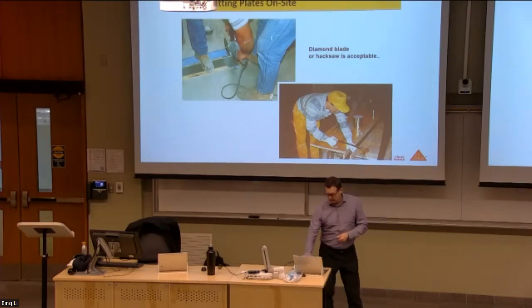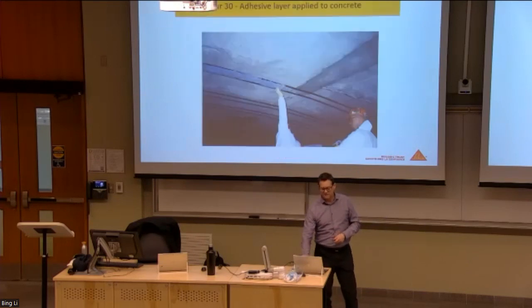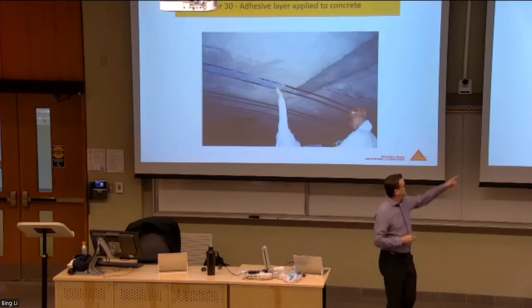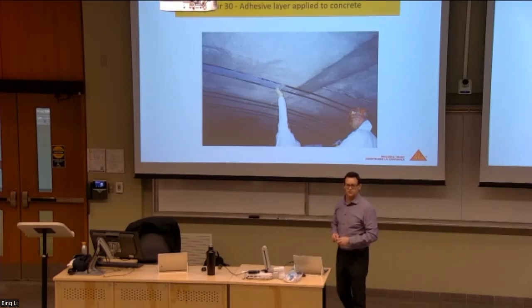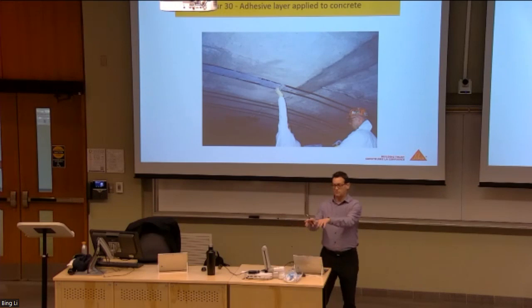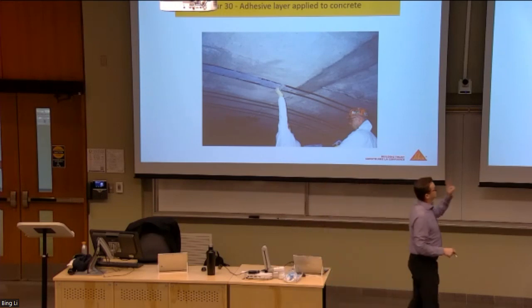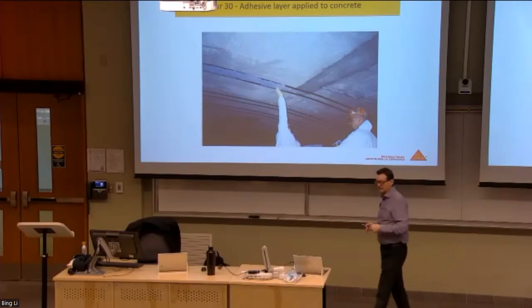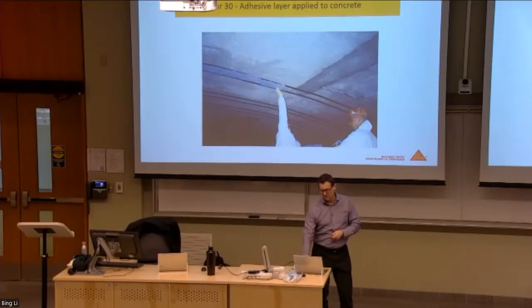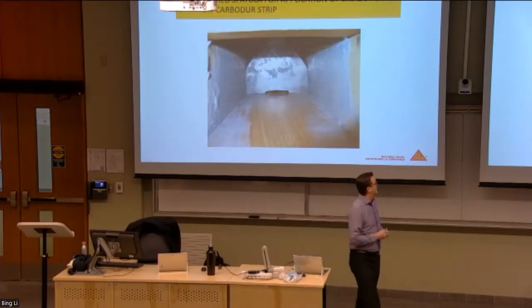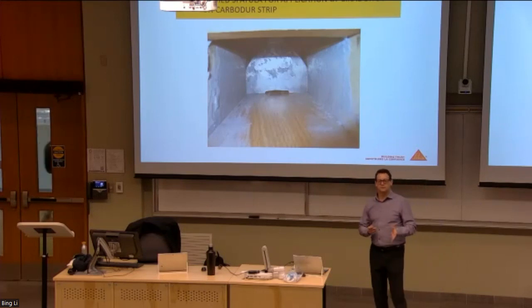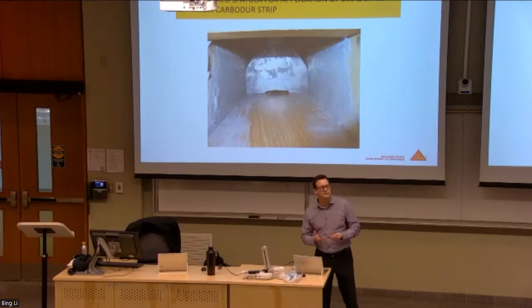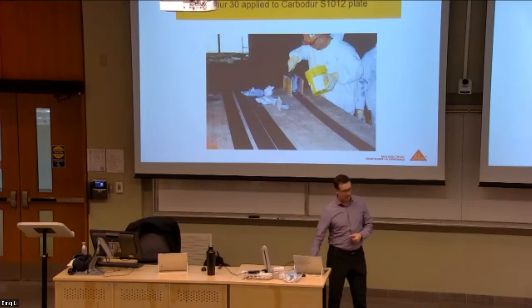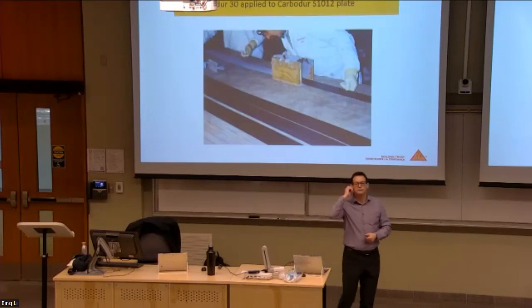Then these are simply cut on site very easily. There's an epoxy adhesive layer which goes onto the underside. Those two lines are duct tape, actually, just to control the cleanliness of the application. High-tech duct tape, right? Once they've applied a layer of epoxy adhesive onto the underside, they construct this jig and deposit the epoxy paste, which would have a loose peanut butter consistency. They dump it into this box and push the material along, and it deposits the material onto the backside of that plate.